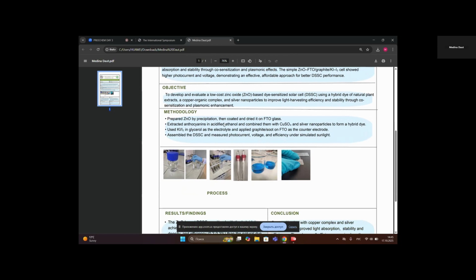So my main methodology was preparing zinc oxide by precipitation, then coating it and drying it on the FTO glass, extracting anthocyanins in acidified ethanol and combining them with copper sulfate and silver nanoparticles to form a hybrid dye. Using potassium iodide and glycerol as the electrolyte and applying it to the graphite, as you can see here, on FTO as the counter electrode, assembling the DSSC and measuring photocurrent, voltage and efficiency under simulated sunlight. I used an ammeter and voltmeter.